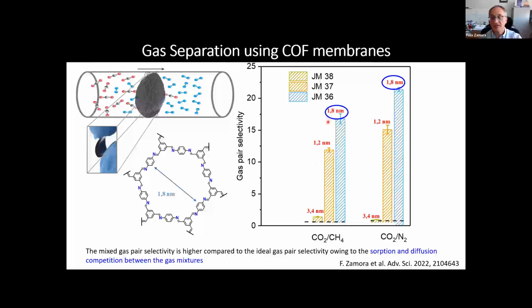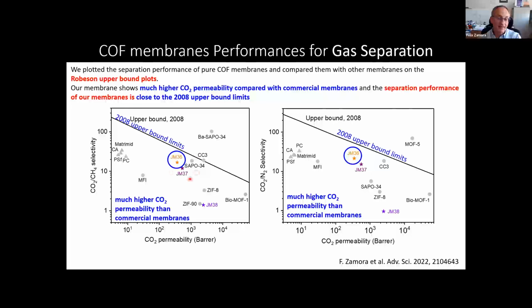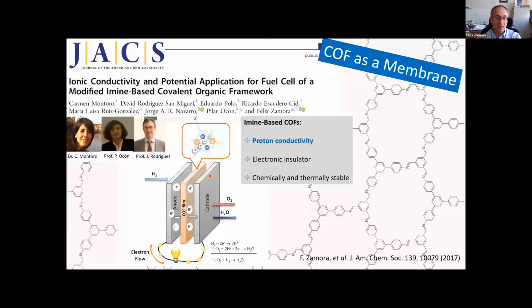If you analyze our results, taking into account the upper bound limits, the Robeson upper bound limits, we observe that we have several membranes with much higher CO2 permeability than even some commercial membranes, and we are close to these limits. So, this first result was quite nice. What can we do additionally with these membranes?